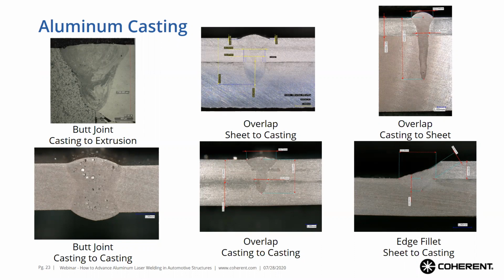In the center area, in the top right, you'll see an overlap weld done from sheet to casting as well as casting to sheet. The image in the top right is actually a 7 millimeter deep weld from casting into sheet, which is also something pretty difficult to do with standard lasers. All of these were again achieved with the arm fiber laser by being able to tailor the beam shape and the parameters. All successful welds. Also done, as you can see, on an edge fillet and a casting to casting in overlap configuration.